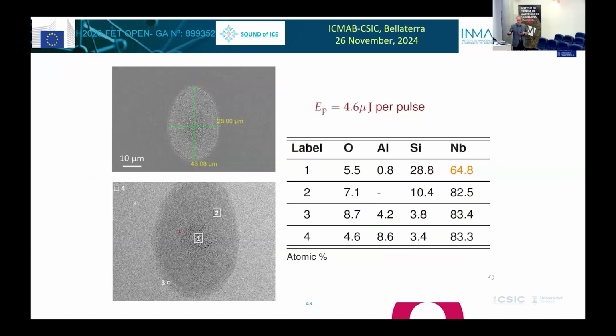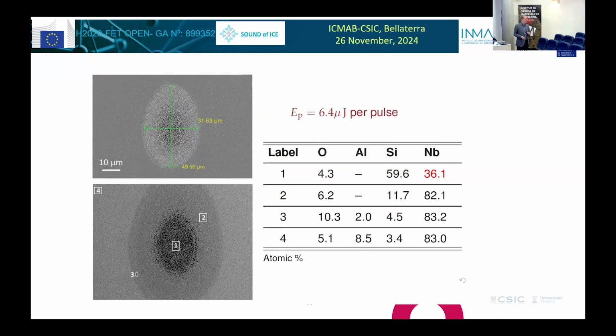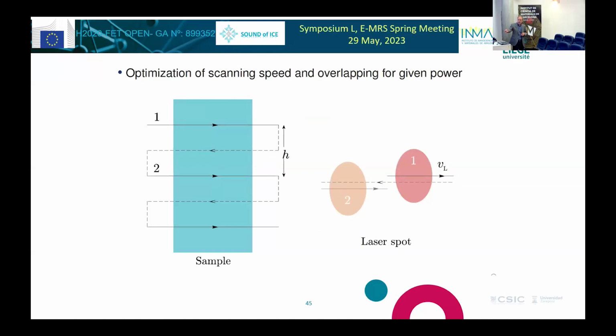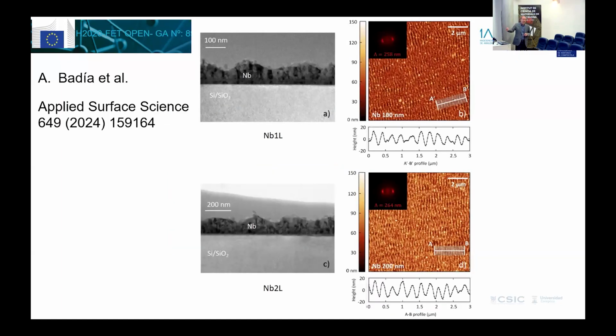We make a measurement with MOI, that's magnetic optical imaging, and we can see how the flux, I'll show you in a moment, penetrates the film. This is what we do to avoid damage to the niobium. So we first do some single pulse damage and see where we are penetrating completely the niobium layer and get into the silicon substrate. So once we do that, we know how to scan the system, and we can do large areas of the niobium film. And with those large areas, get these very nice LIPS, laser-induced periodic surface structures.